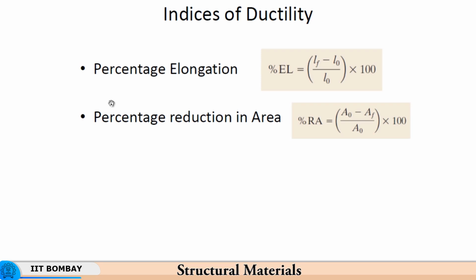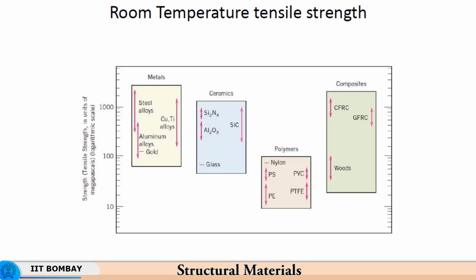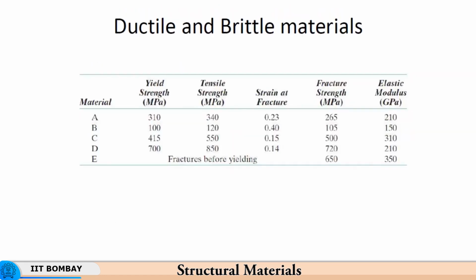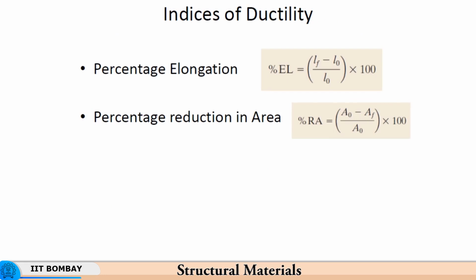So, if your sample is microns thick, for the same material you will get a much lesser percentage of elongation. For a thicker material you will get more percentage elongation. So, this is influenced by size effect. If you look at the value of n, that is strain hardening exponent, that is a much better estimate of ductility and index of ductility, because that tells you the extent of uniform strain that you are going to get in a plastic deformation regime.